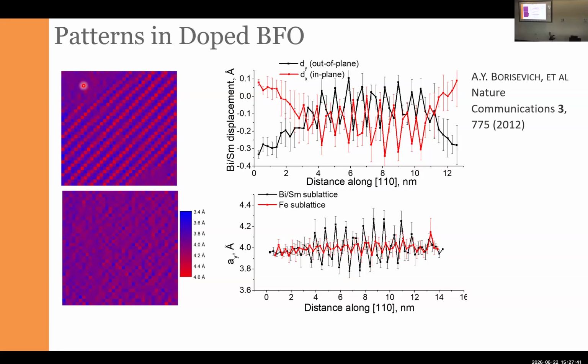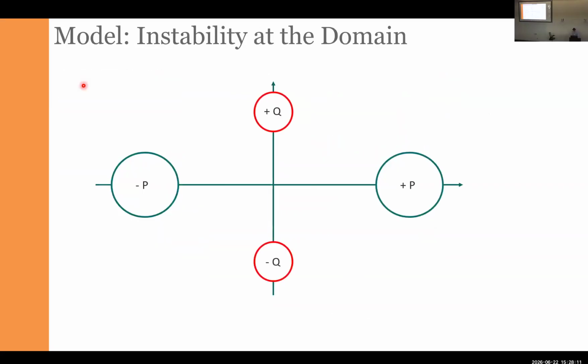And in some locations, all of a sudden, you start to have these periodic patterns oriented in arbitrary directions. Again, scattering methods are not going to detect this, because imagine you have a uniform region, and then these patterns start to form in different locations in a more or less disordered fashion. Microscopy can resolve them because they are localized, but for scattering, since their relative positions are random, you will not be able to see them anymore. Again, the question always becomes, where does it come from and what does it mean?